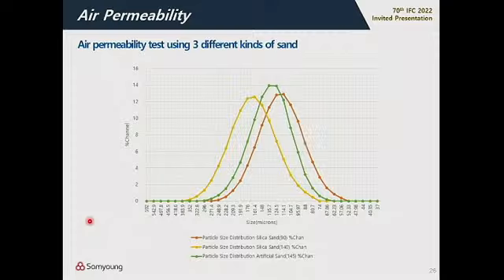In addition to that, we did an additional air permeability test using 3 different kinds of sand. This is the particle size distribution difference for the 3 kinds of sand. This color is the particle size distribution for silica sand 140, this is for the artificial sand 145, and this color is for the silica sand 90. The number means the diameter of the sand.